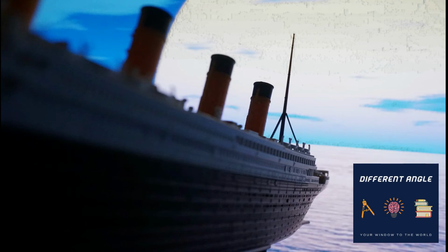However, when the coupon of the Titanic steel was tested, the pendulum struck the coupon with a sharp ping, barely slowed, and continued upon its swing. The sample, broken into two pieces, sailed across the room. Results of Charpy test after exploration of why did the Titanic sink. Figure 3, results of the Charpy test for modern steel which was left unbroken, left, and Titanic steel which split into two pieces, right.